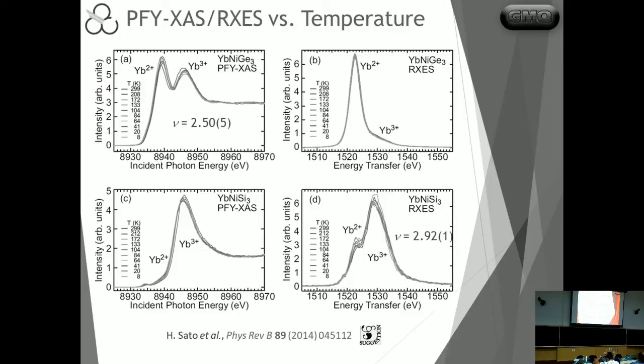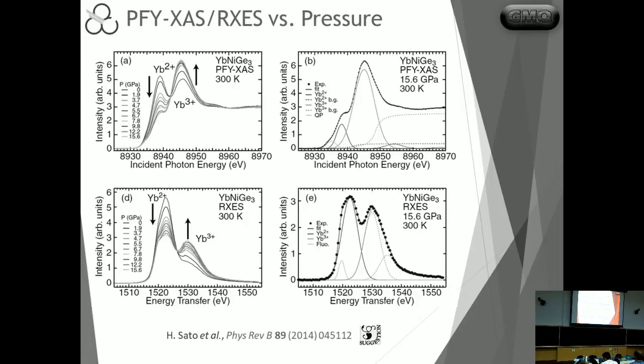On the other hand, when you look at the PFY for the silicide, you basically don't see any of the 2+ signature. When you go to the RXES, you do see a reasonable peak for the divalent one, and based on this analysis we can get a better precision and show that the effective valency is really around 2.5 for the germanide, while the silicide is around 2.92. There's a very small temperature dependence here. It just varies a little bit as we go from room temperature down to about 8 Kelvin. But in terms of pressure, we can see some important differences.